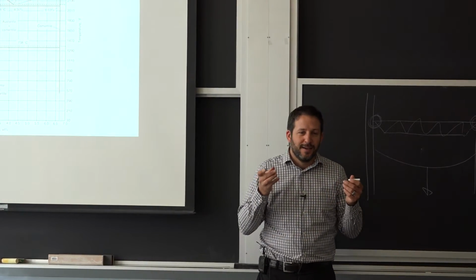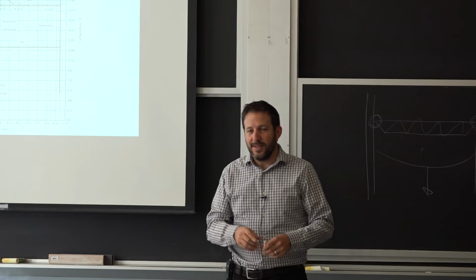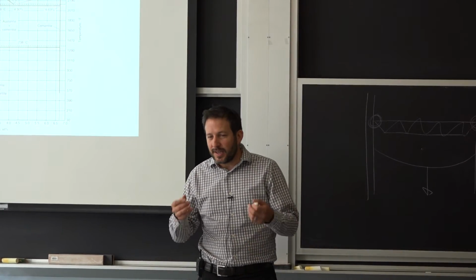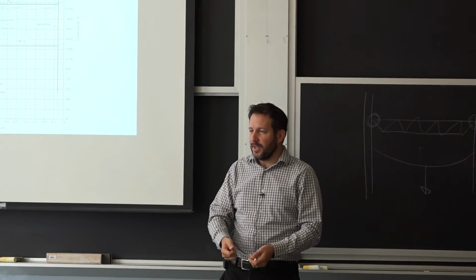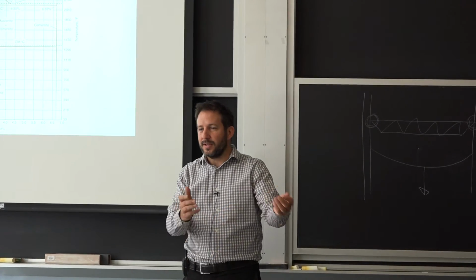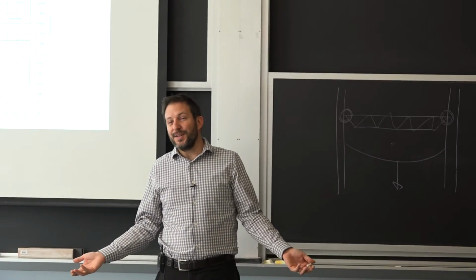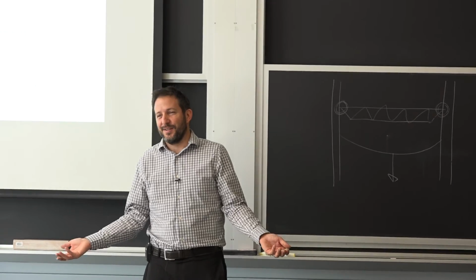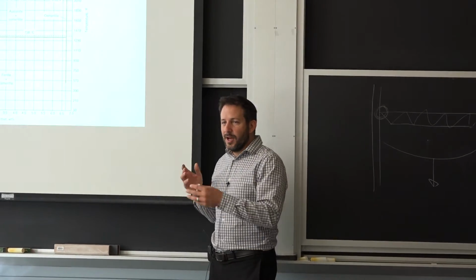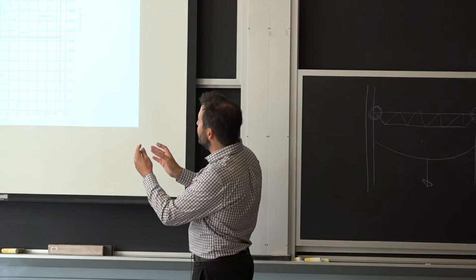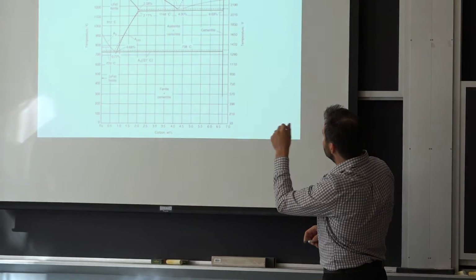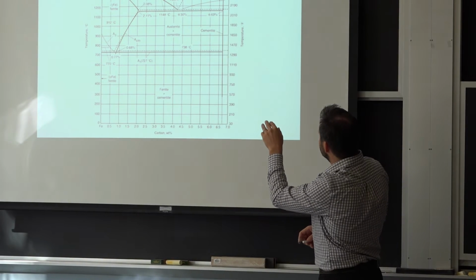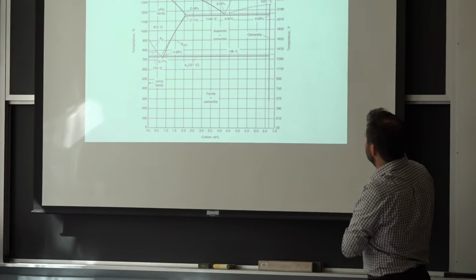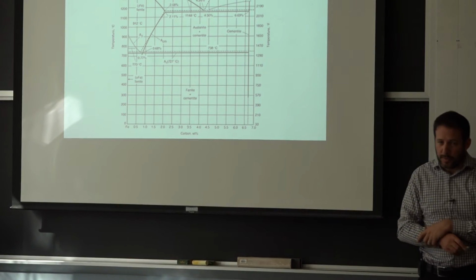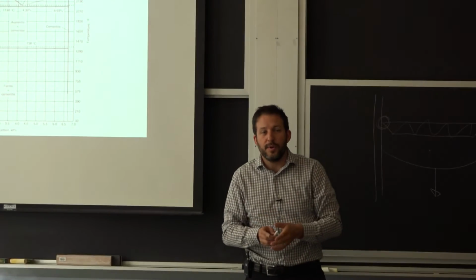So why, very long ago, 16, 17, 1800, was cast iron so dominating for how you make cooking pans, how you make stoves? Guess what? They couldn't melt it without killing themselves. So the combination of adding the carbon to the iron takes down the melting point. If you go all the way to the left, it's 1550 or so, and then it takes it down to below 1200.